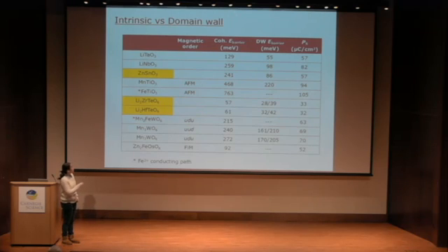So those are all the results we calculated. If we compare these two columns, we see that the domain wall barrier is much lower than the coherent barrier. And here are the materials that have lower barriers in both cases. For this iron titanium and this iron tungsten material, I put a star here because we find in the calculation the switching path becomes conducting. So the path is more subtle and needs more research.